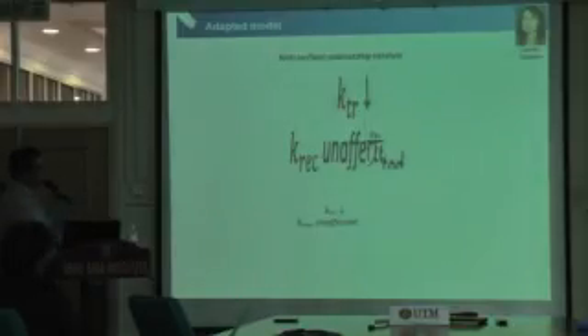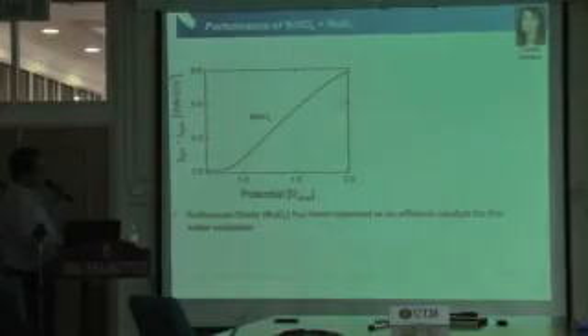Anyway, what we then try to say is that if we put a non-surface passivating catalyst, some catalyst that we know is a very good water oxidation catalyst in the dark, but it does not passivate the surface, we would expect the recombination rate to stay constant, because it's unchanged, it's not passivating, and the charge transfer rate will still go down because you just replace this with a different level, with different materials, right? So we tried ruthenium oxide, because ruthenium oxide has been reported as a very efficient catalyst, but it is unexpected to passivate the surface of bismuth vanadate.